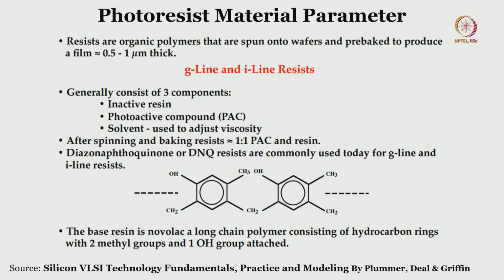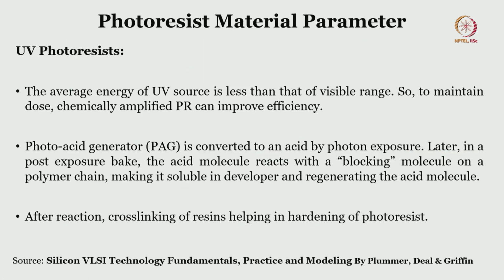Okay. So, let us understand the UV. The average energy of a UV source is less than the visible range. So, to maintain those, chemically amplified photoresist can improve the efficiency. These are material parameters of the photoresist. Photoacid generator or PAG is converted to an acid by photon exposure. Later in the post exposure bake, the acid molecule reacts with the blocking molecule on a polymer chain, making it soluble in developer and regenerating the acid molecule.